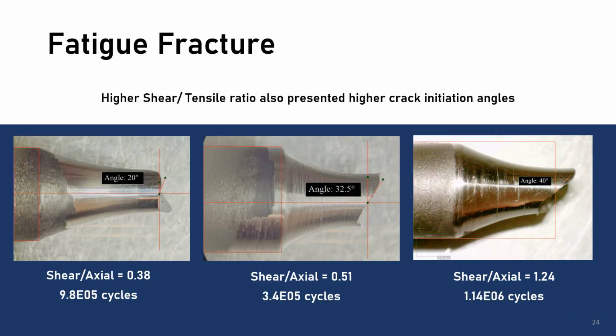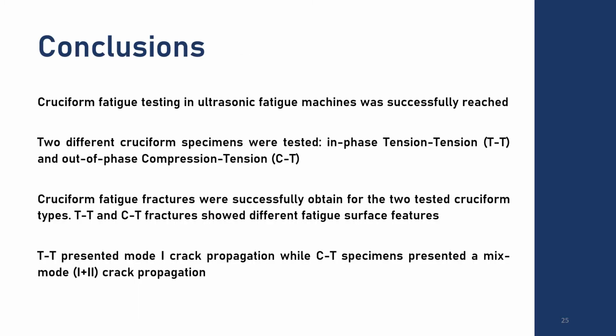Now, for all specimens, we also measured the crack initiation angle in relation to the axis of the specimen. We can clearly see an increase of the crack initiation angle with respect to the axis for higher shear and axial ratios. Now for conclusions, first focusing on cruciforms.